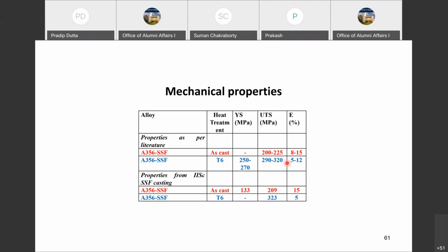Of course, the elongation part, we were at the lower end of it once we did the T6. Of course, before the heat treatment, the elongation was more. But we are still in the range which was predicted, because elongation of course decreases after the heat treatment is done.